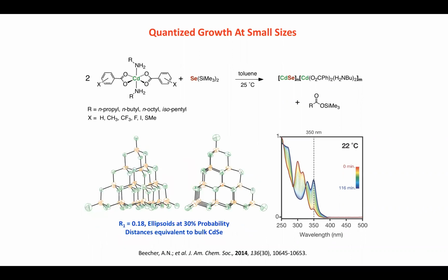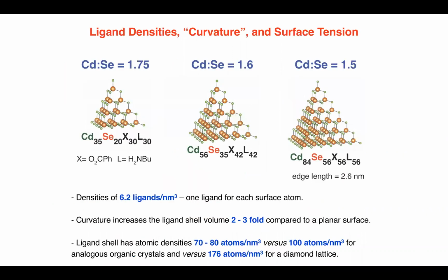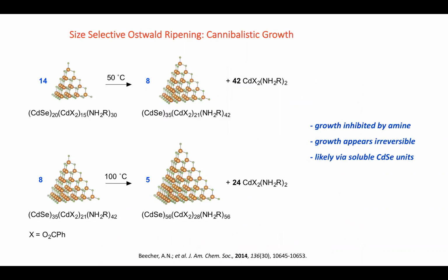Okay, so a few of the things, I think I included slides on that. A few other things about this reaction. It's irreversible. So this is a process that appears to be downhill overall. And so we think the temperature that's required here is really a matter of kinetics. Getting from this object to this object is limited by some kinetic barrier that you have to cross. And it is inhibited by ligands. This is maybe more important.